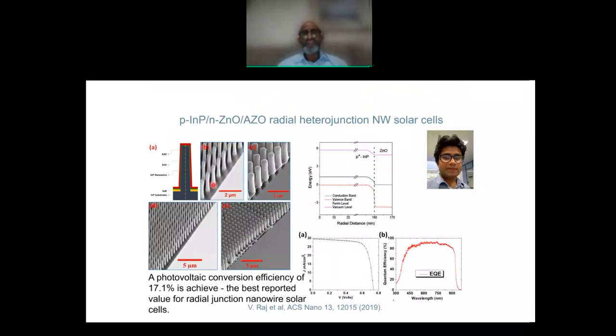Instead of making p-n junctions within the same material, he made the p-type indium phosphide by MOCVD, and then coated it with the n-type zinc oxide and aluminum doped zinc oxide using atomic layer deposition, so that you're really creating these so-called core shell nanowire solar cells. To cut the long story short, we were able to demonstrate about 17% conversion efficiency of these particular solar cells. And my colleagues tell me these are the best reported values for the radial junction nanowire solar cells.